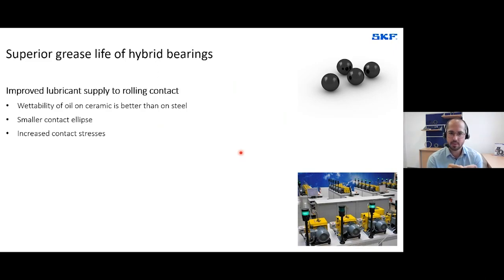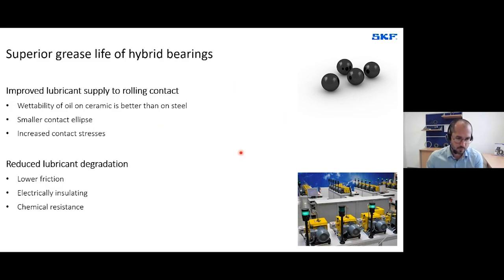The contact ellipse is smaller, which makes it easier for the oil to move into the rolling contact. And it also has slightly increased contact stresses, which is favorable for grease bleeding, for example. And besides the improved lubricant supply, it also has a positive effect on lubricant degradation because it is simply reduced. Hybrid bearings have a lower friction, which causes lower local temperatures in the rolling contact.